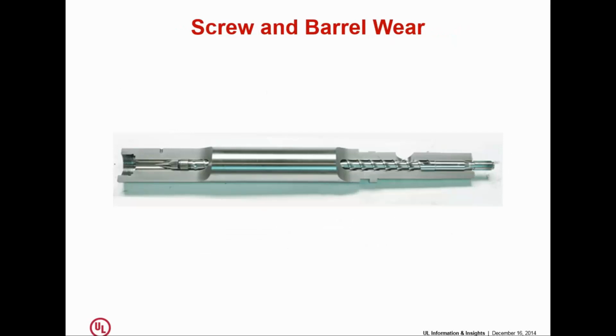Now, screw and barrel wear. This is a nice cross-sectional view of how the screw and the barrel fit together. Notice it's very long, and it's very small in diameter. So obviously things like straightness and concentricity are very, very important. Because these materials are going to be very, very close to one another, ideally just 2 or 3 thousandths difference between the outer diameter of the screw and the inner diameter of the barrel. You want compatible materials in case they do rub against one another.